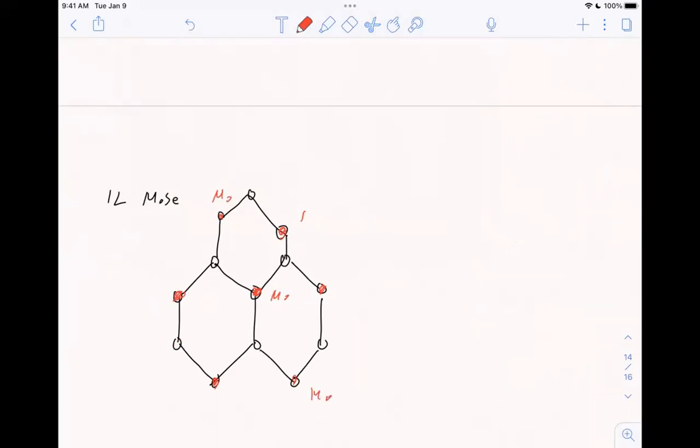Okay, so the Se atoms in our model are not participating. In reality, a small part is participating. That's why you have a small spin-orbit coupling, which is due to the P orbitals in the Se atom, partially. Because we only use a 2-band model, but there are more bands. They open a small gap in the conduction band that is not in our model. We did not capture that, but this is relatively small.